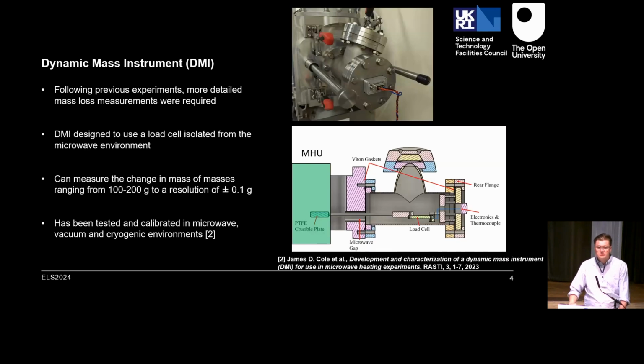One thing I did notice was that, quite obviously, if you adjust the heating time, you can change the amount of water coming out. What I did find was that the rate of water extraction would change over time. At the time, I was simply measuring the mass before and after taking it in and out of the microwave chamber, which wasn't the most efficient way of doing so. And we couldn't guarantee that the samples between each type were consistent, or that all the properties were consistent.